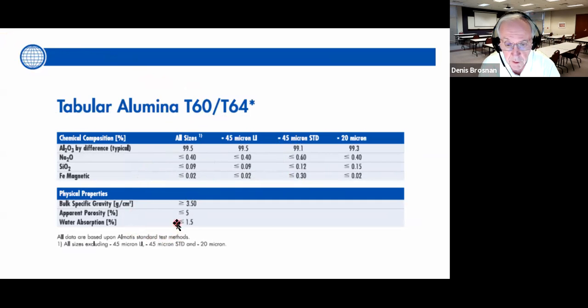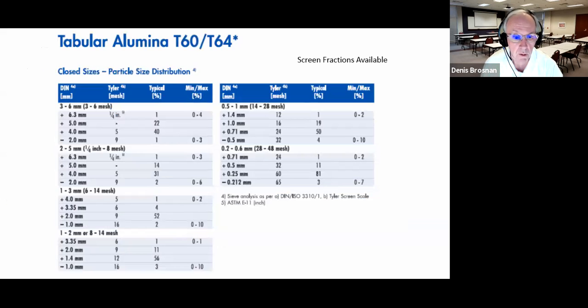The aggregate is porous. It has a little less than 5% porosity. If you polish this and look at it on a microscope, you will see some pores within the corundum crystals. So that's kind of what you expect with tabular alumina. It's available in different particle sizes from the supplier, or you can buy it as aggregate and crush it yourself.